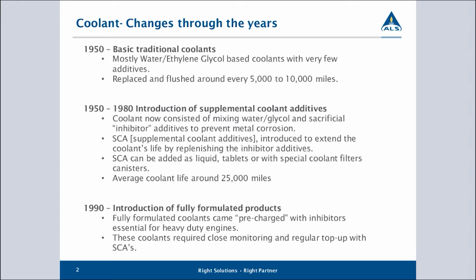So these additives, because of the way they work, are what we would refer to as a sacrificial additive. And what we mean by sacrificial is that they get consumed in service. So you put the coolant into service. Initially, all these additives are available to work, but as the coolant is being used in the system and reacting with oxygen, the additives start to become inactive. And so you would need to change these coolants quite frequently just to replenish the additive levels in there.